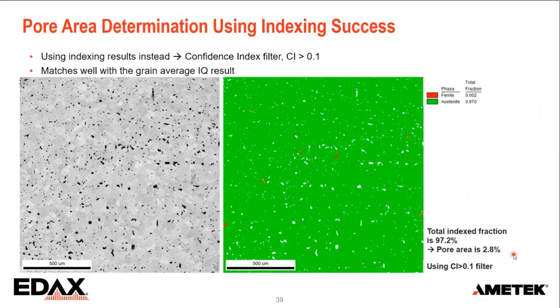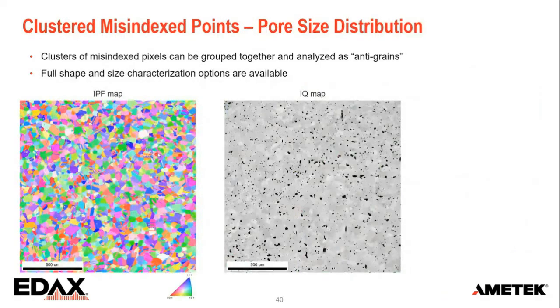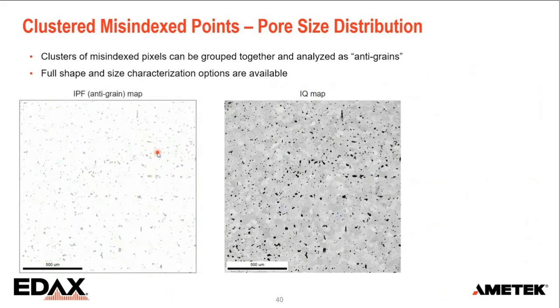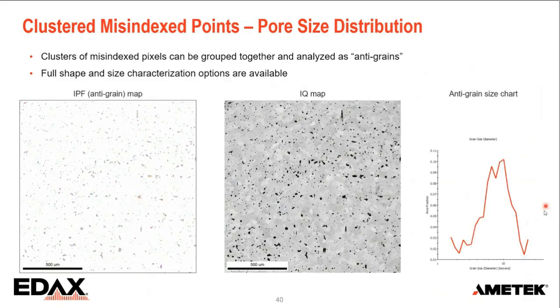Now, we can go a bit further than that, because once we have identified where the pores are, we can also look at those in more detail. So we can have these groups of points. And once we have that, we can tell the system, okay, group these together as if they are grains. And we call that anti-grains. So instead of just throwing these points away, we can actually quantify the pore size distribution.